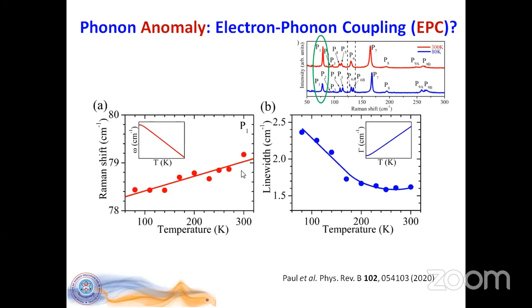Before we go into the data, I would like to request you to focus on the insets of this frequency versus temperature plot. As we also discussed for the other modes, as we increase the temperature, the frequency should decrease for a phonon, which is what the anharmonic model would predict. And similarly, the line width of the mode should increase with increasing temperature. So that is what is expected.